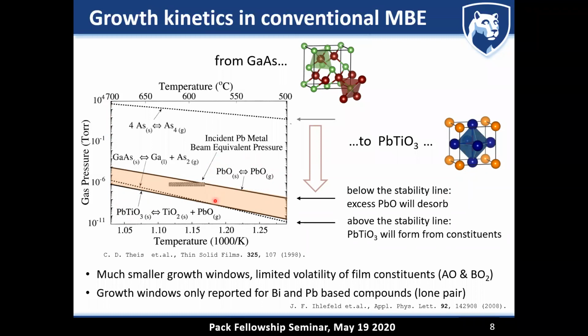Okay, so this much smaller growth window turns out is only going to be accessible and only going to be there if one of the constituents of the complex oxide films, in this case lead oxide, is also volatile at the growth conditions or the growth temperatures you're using. Typically here 500 to 700 degrees C. And it turns out that for the complex oxide materials that we are typically interested in, there's only one or two elements that actually deliver on this. The one is bismuth, which is interesting because for the growth of the multiferroic bismuth ferrite, that comes in handy. And it also is true for lead. And that's interesting for growing things like PMN-PTs or piezoelectric and ferroelectric materials.